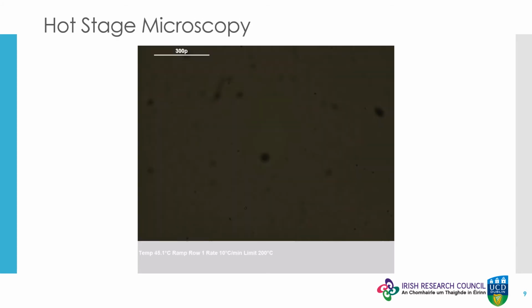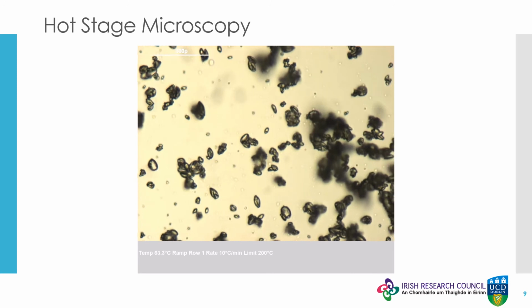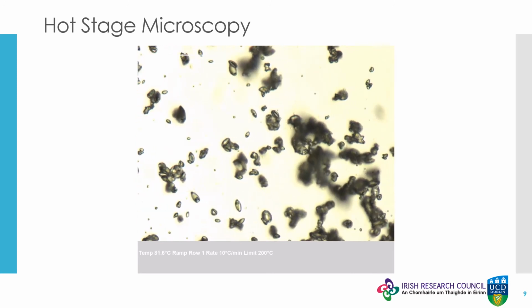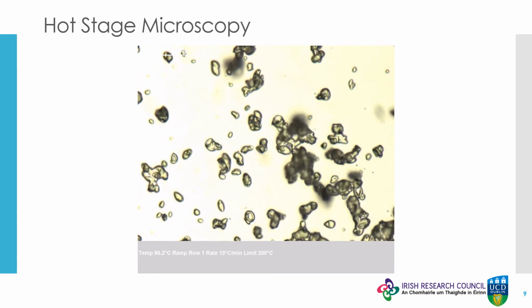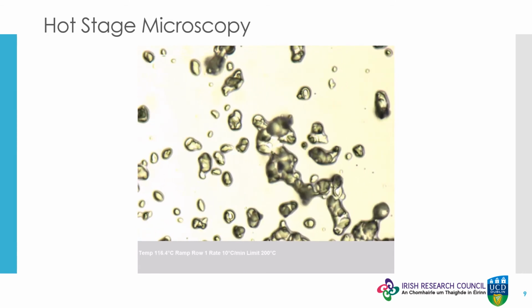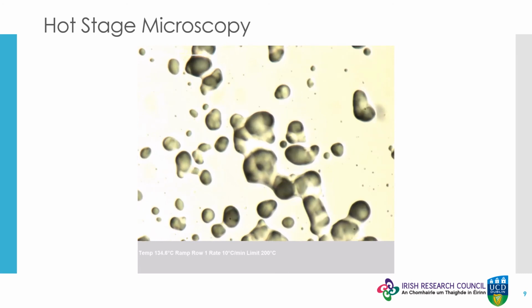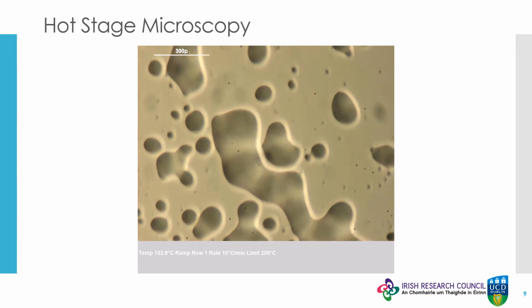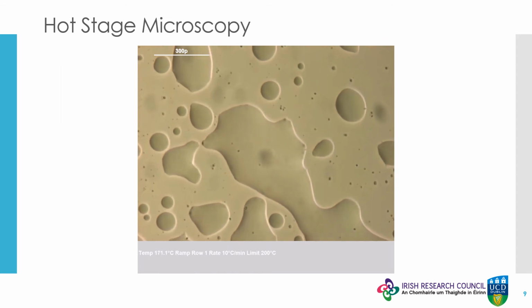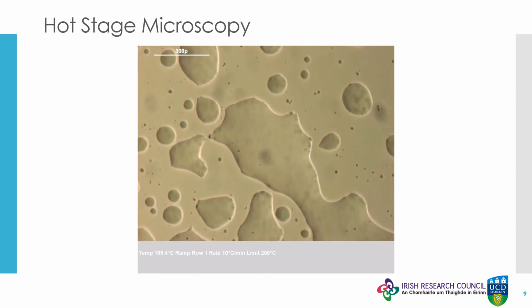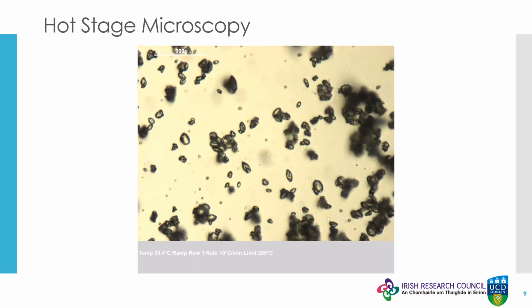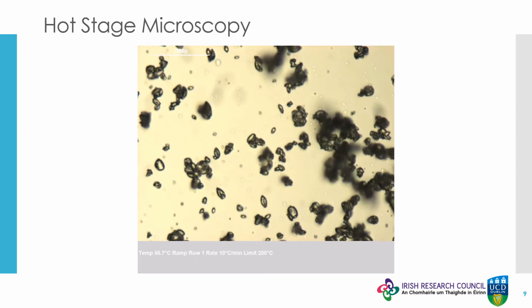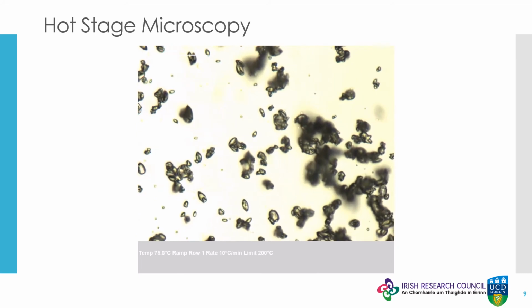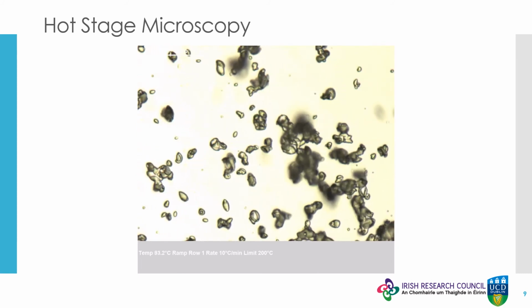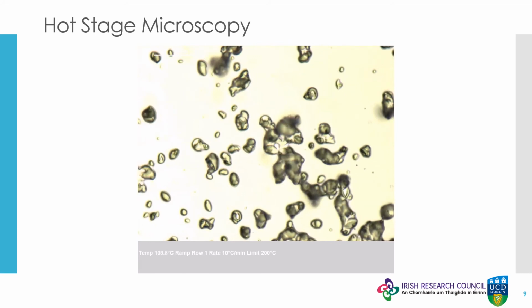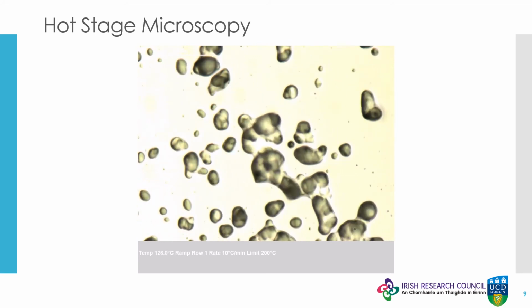To investigate this theory, hot stage microscopy was used to monitor the nature of the material as it undergoes heating. In this example, the product composed of the low molecular weight polymer and containing 50% weight-for-weight API-IL confirms the hypothesis. Initially, the formulation appears to be a solid powder, until a liquid emanates from it at around 85 degrees C. Heating the sample further, we can see that the liquid starts to dissolve the polymer at around 115 degrees C and completely solvates it by 125 degrees C. These observations were true for all compositions and verified that the API-IL is initially phase separated from the polymer.